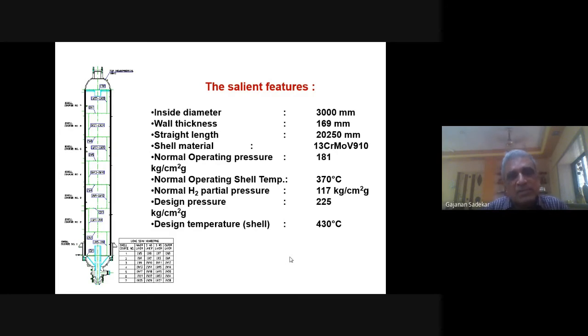And then along that mixture flows to the further. Now this equipment, as I said, with thickness 169 mm, is a very interesting thing. The shell material in this particular case was 13 chrome moly vanadium steel. It's called chrome moly vanadium steel, and it is very high strength. So if I had to use, suppose, 2¼ chrome 1 moly steel, the thickness would have been around 250 or 300 millimeters, whereas this material is a very high strength material.